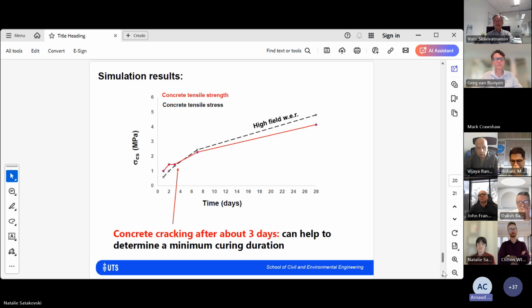And I think it can also be very useful to design the minimum duration of concrete curing. Applying curing is a good way to limit a lot of drying shrinkage. There's still autogenous shrinkage going on. But if you apply curing for 3 or 4 days, it's likely that it will delay the increase of the tensile stress in the concrete for 2, 3, 4 days. And when drying shrinkage starts again, that will leave enough time for the tensile strength of the concrete to be high enough and avoid cracking.